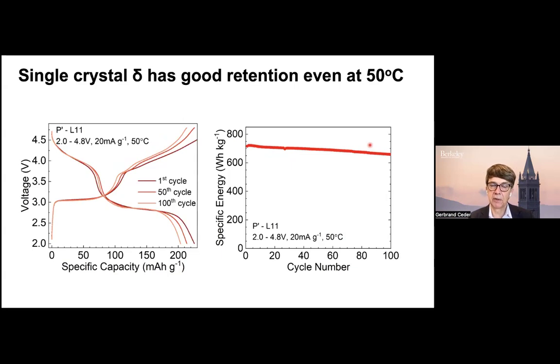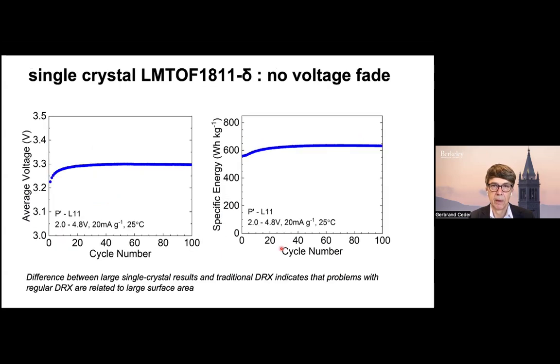Even at 50 Celsius, these materials have good retention. There is a little bit of capacity fade at 50 C, but this is still not all materials fading. Some of this is actually due to major issues with EC breakdown, electrolyte breakdown, at 4.8 volt. The newer charging protocols of Delta only go to 4.6 or 4.7.